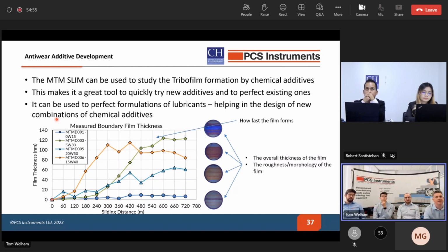We have some fluids that form very little or no film, and then we can see how some take slightly longer to start building up the film thickness, and others that form earlier and actually are slightly unstable. So there's a bit that's sort of worn away as the test progresses. And as well as the average film measurement, which I'm showing here, which is an average of an area of the contact, we can also use the provided software to give us a full map of friction across the entire contact.